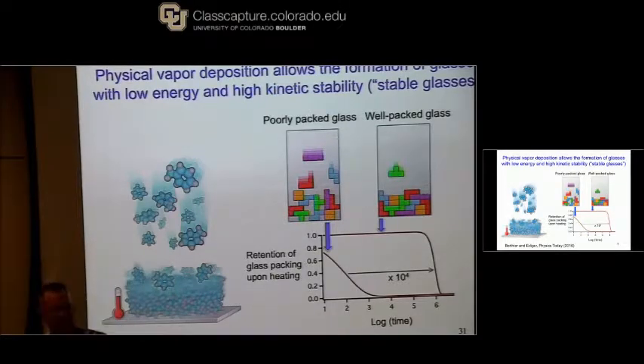Yes? So I guess the speed, the diffusion, the velocity, ability to diffuse versus the deposition rate is what makes the difference between left and right. Right. So yes, there's sort of 2 time scales in the experiment, at least. One is how fast molecules can explore different packing arrangements at the surface, and the other is how fast the molecules are coming down. So in a typical experiment, we're depositing a monolayer of molecules about every 5 or 10 seconds. And so we think that the mobility extends maybe 2 or 3 layers into the material. So you can think each molecule has 5 to 15 seconds in order to sample different ways of packing with its neighbors.